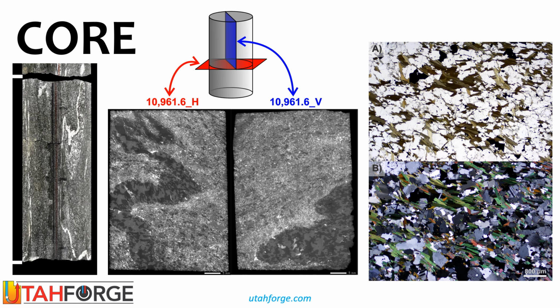This sample comes from near the toe of 16A at 10,961.6 feet, also shown in two orientations at center. In these SEM images, you can see the dark colored, coarser grained vein or dike that has been folded. That's the white colored line in the exterior core photo.